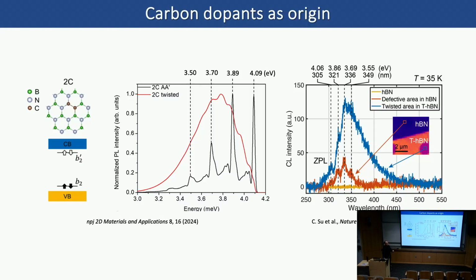Which one is better? From a CL perspective, we've never seen any emission spectrum coming from a monolayer hBN, which is a common phenomenon across the whole 2D material. Even for MoS2, when you make it freestanding, CL doesn't show anything unless you encapsulate it in hBN. So that's a bad thing. But the good thing about monolayer is that it gives us a clear atomic structure. So when we scan across it, we know what the atomic structure is, whereas for bulk material, you don't really know what that defect is.